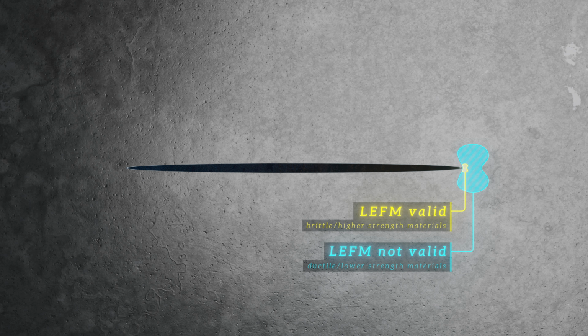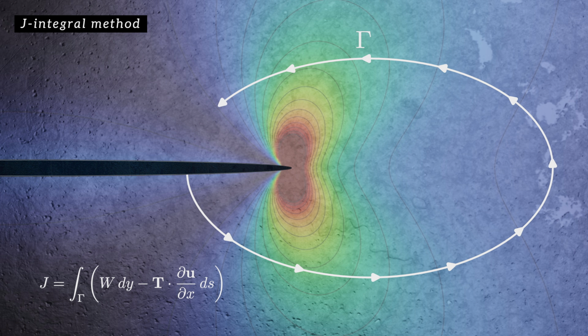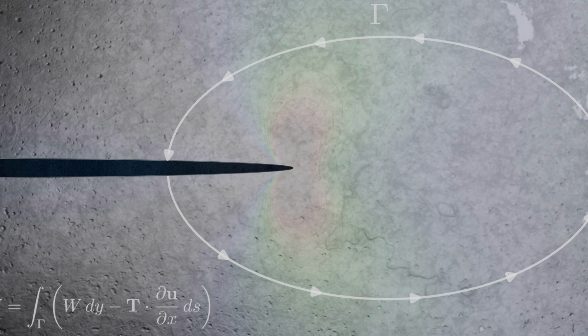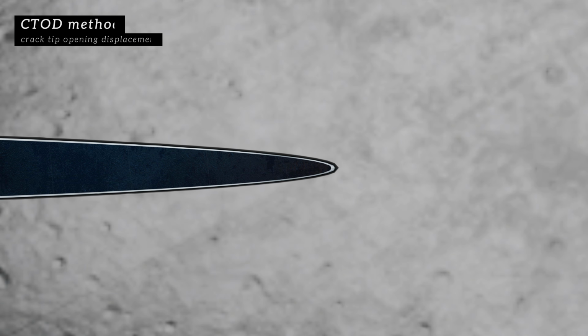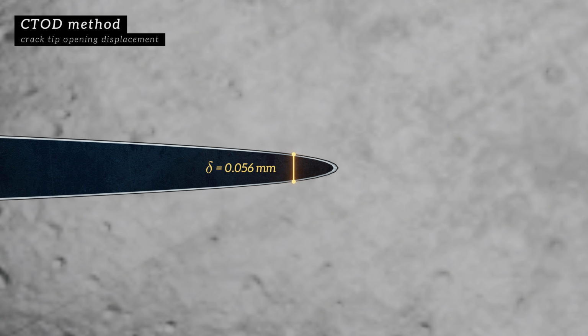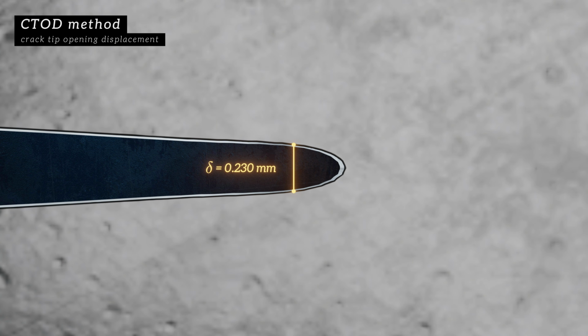In these cases, a more complex elastic-plastic fracture mechanics approach is used. One such approach, the J-integral method, involves calculating an integral along a contour path encircling the crack tip to determine how much energy is available to drive growth of the crack. Another approach, the crack tip opening displacement method, involves measuring how far apart the two faces of the crack move at the crack tip when a load is applied.